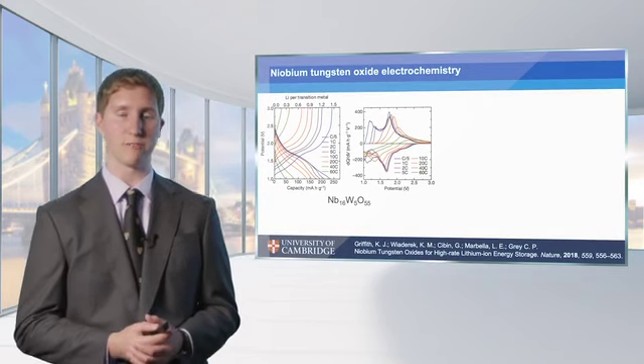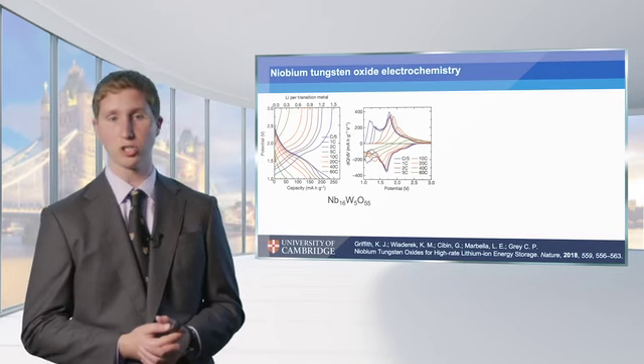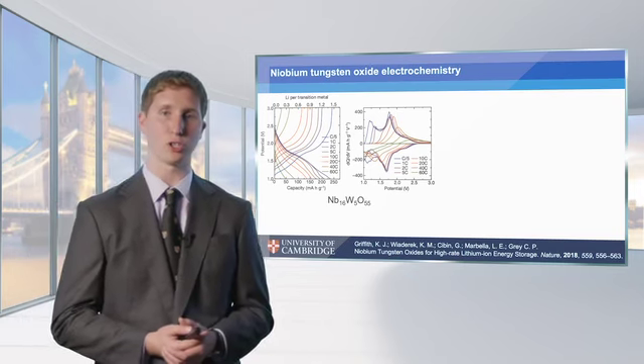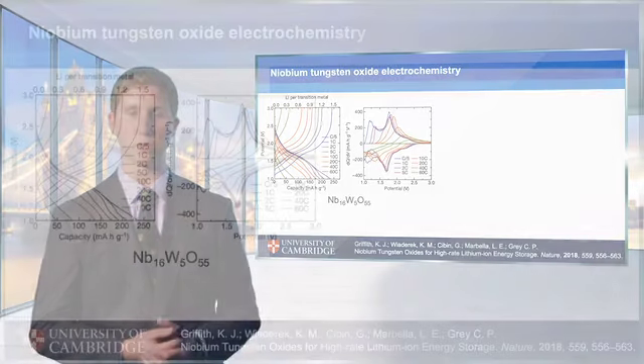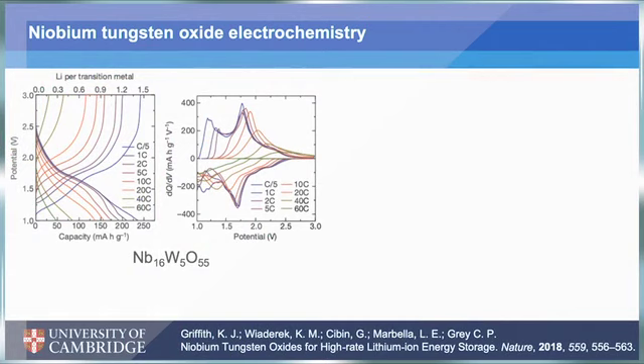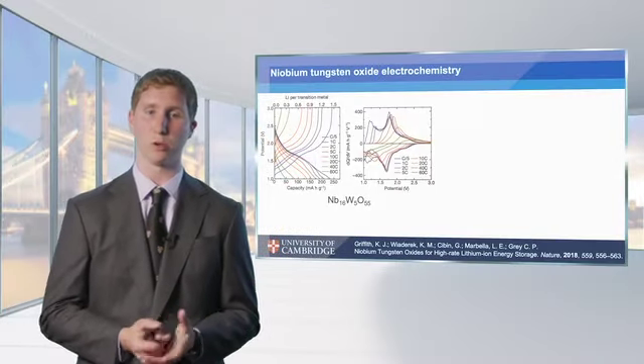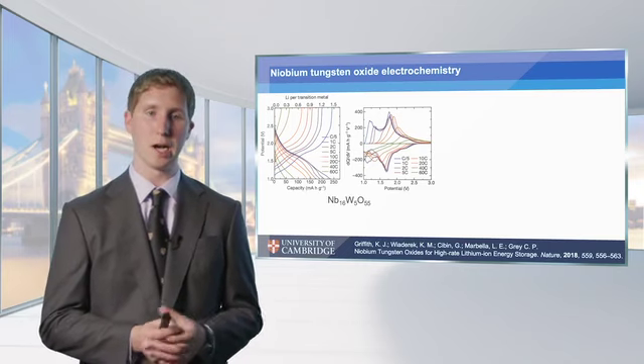And so here we're looking at this as a function of rate, going all the way from a 5-hour charge discharge up to a less than 1 minute charge or discharge half cycle. And so we can see that there's a relatively weak dependence on rate, where even at say 10C or 20C, which corresponds to 6 to 3 minutes for a charge or a discharge, we're able to access almost 150 milliamp hours per gram and nearly a full lithium and electron transfer for every transition metal we have present. So for every niobium and tungsten, we're getting at least 1 lithium and electron out. And at lower rates, we're actually exceeding that significantly, which means there must be multi-electron redox chemistry happening. So either our tungsten and/or our niobium is providing us with multi-electron redox capability, a question that we definitely want to explore a little bit later on.